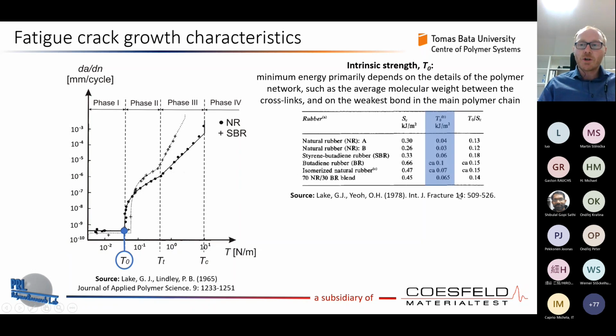This table was shown as well by Chris. However, I would like to show it once again, and you should really concentrate on the T0 values. As Chris told, natural rubber has the lowest T0, styrene butadiene rubber has a slightly higher one, and the highest has butadiene rubber. We can see it here from this work from Lake and Yeoh from '78. And butadiene is almost about 100.